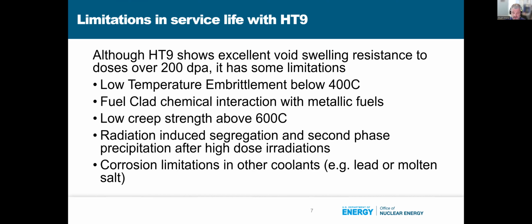And then one of the big issues is low creep strength. Even though HT9 is a really nice material, up above 600 degrees C it does show reduced creep strength, even relative to an austenitic stainless steel like 316L stainless steel. So can we develop, especially if we're trying to have materials for some of the advanced reactors like the molten salt reactors, where they want to go out to maybe 700 or even 800 degrees C, we really would need to improve the creep strength to use a material like this for that application. And then you also can run into radiation-induced segregation at high doses, and also some second phase precipitation.